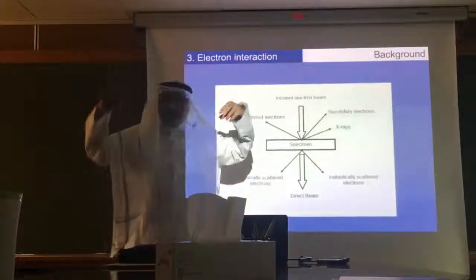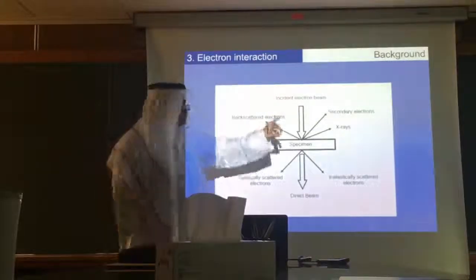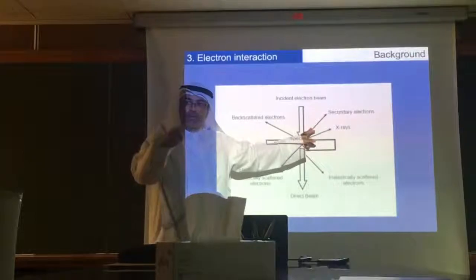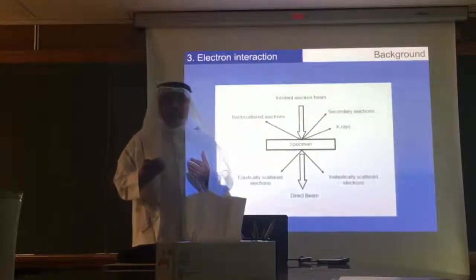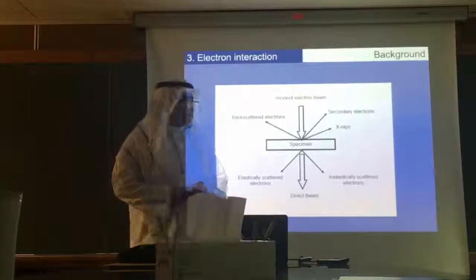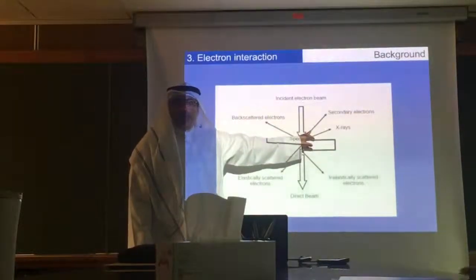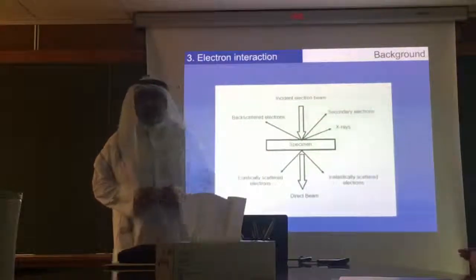In the scanning electron microscope, there are two detectors. One can collect only the backscatter, and one can collect the secondary and the backscatter. But the secondary is much more. So the picture will be coming from the secondary, actually, not from the backscatter. This is very good for the morphology and topography. And this one is very good for the contrast.